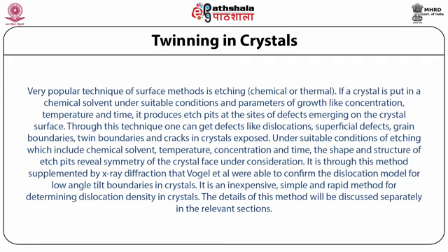It is through this method, supplemented by X-ray diffraction, that Vogel et al. were able to confirm the dislocation model for low-angle tilt boundaries in crystals. It is an inexpensive, simple, and rapid method for determining dislocation density in crystals. The details of this method will be discussed separately in the relevant sections.